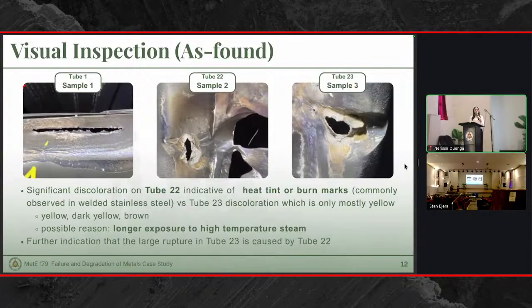However, for sample 3, the discoloration is mainly yellow, and for sample 2, the discoloration includes yellow, dark yellow, and brown. These are indicative of heat tints or burn marks, which may be caused by longer exposure to high temperature steam, which is, again, further indication that the large rupture in tube 23 is caused by tube 22.